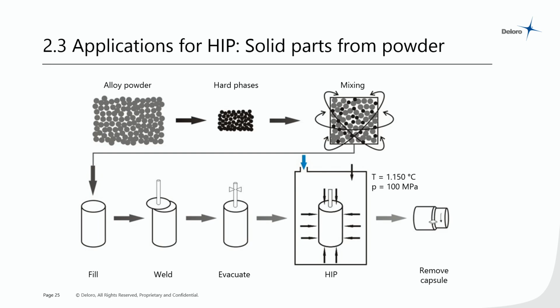How does that work? Effectively, as you can see on the bottom here, you have typically a mild steel can, which is filled with the powder, closed. All of the gas is evacuated out of that can. It is then subject to hipping, and the capsule or the can is removed afterwards. And then you have, in this case, a solid block of some new material.